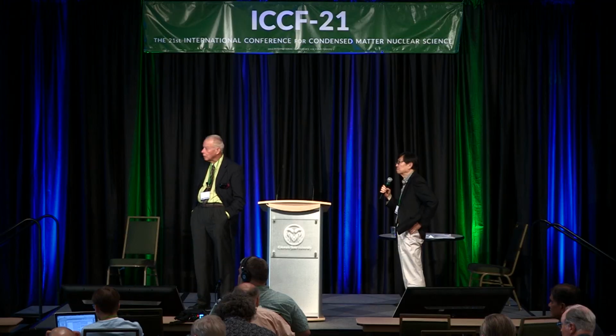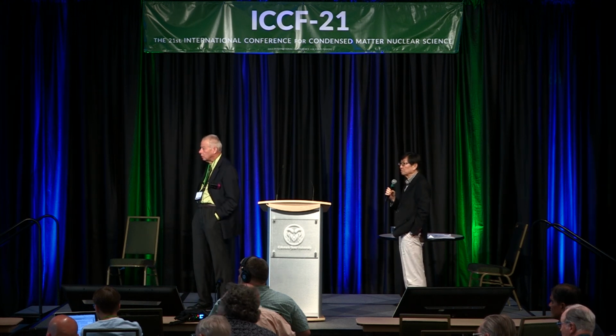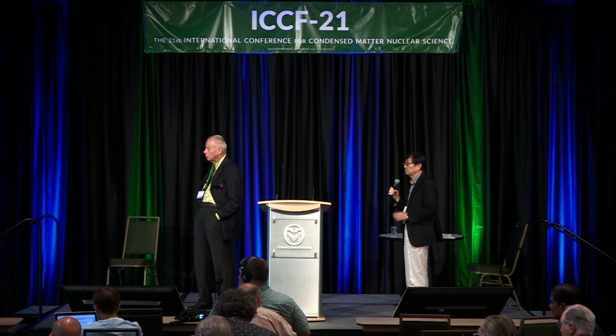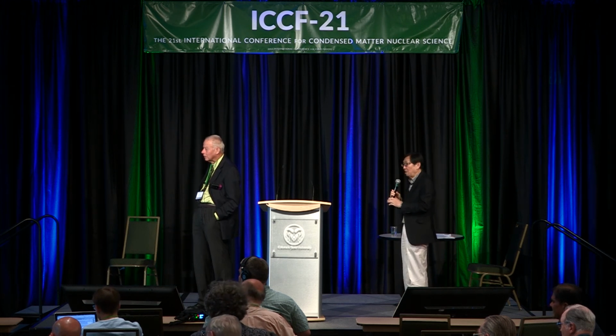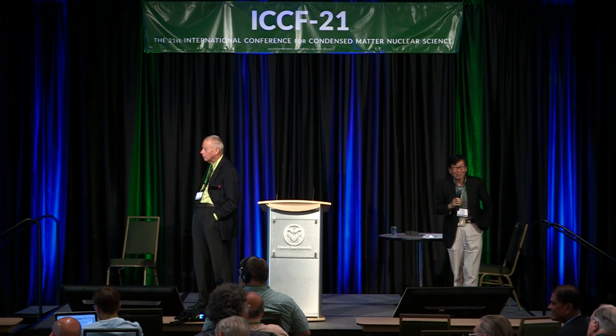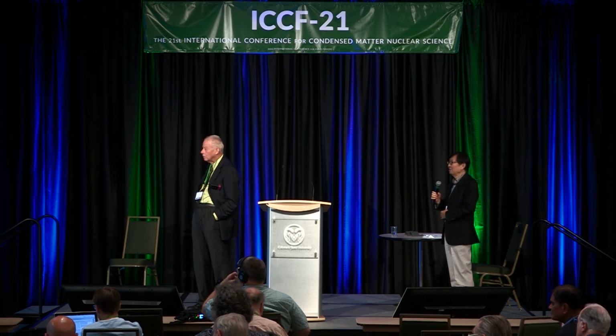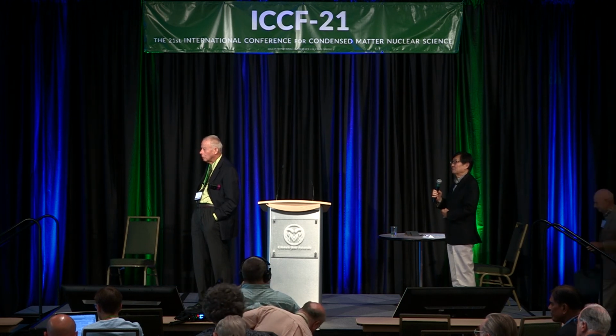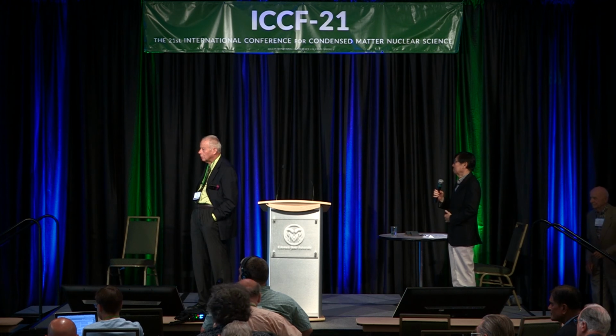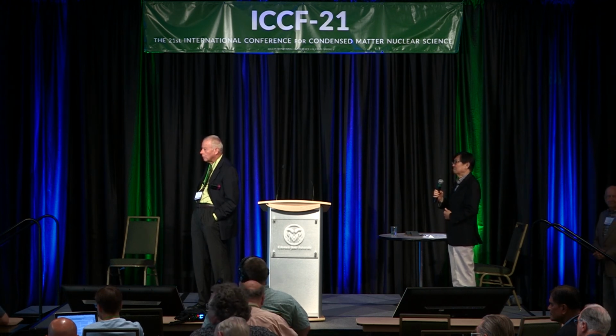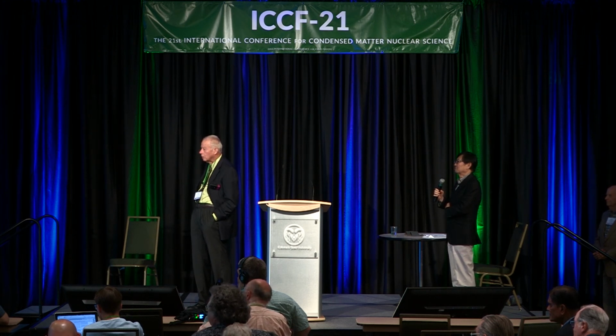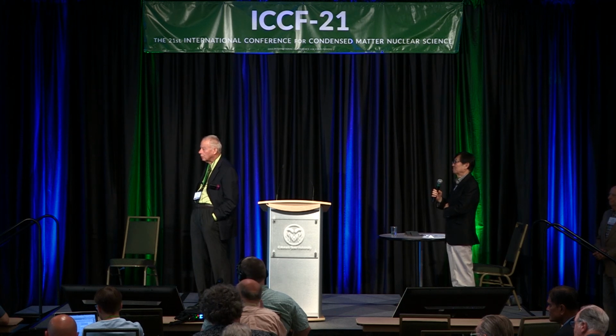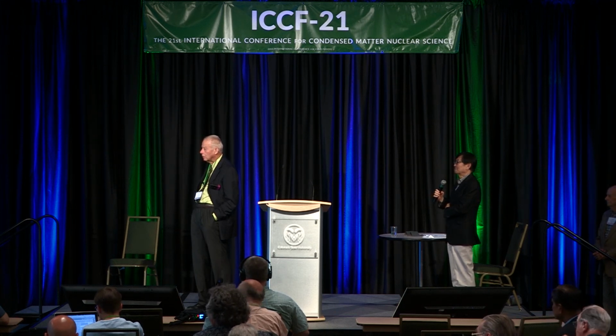Mike? Hey, I'd like you to comment on the following thought, that the magic of boron is that it avoids the need for patience. Right. The effect occurs much more quickly. Some of our pure palladium cathodes have not produced excess heat until 1,000 hours into the experiment. With your palladium-boron stuff, it shows up more or less straight out. Very few people had the patience to run experiments for 1,000 hours. Martin and Stan used to run them for 3 months before they'd abandon them. Yeah, right. So that level of patience is very, very rare in anything, actually, but particularly not in science. Right. Yeah, okay. I agree.